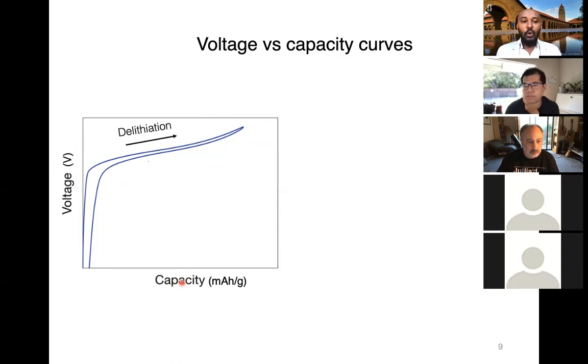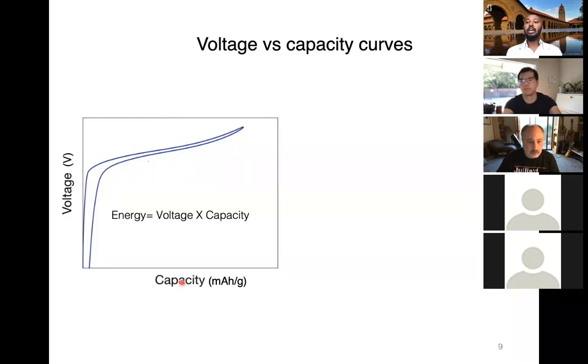And what happens when you move from left to right on this curve is delithiation, removing these lithium ions from the material. What happens when you move from right to left is lithiation, putting the lithium back into the material. And the amount of energy you can store in a given material is given by this formula, which is the voltage times the capacity. In other words, the area under the curve, and I'll come back to this formula later on.